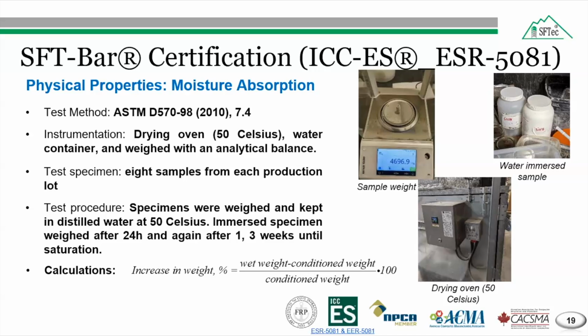The FRP specimens were tested in accordance with the water absorption procedure 7.4 in ASTM D570. The instruments used in the test were a drying oven capable of maintaining the required 50 degrees Celsius, a water container for the absorption, and an analytical balance. The specimens were initially dried in an oven for 24 hours and weighed after cooling in a desiccator. This weight was called the condition weight. After conditioning, the specimens were placed in distilled water, which was kept at 50 degrees Celsius.